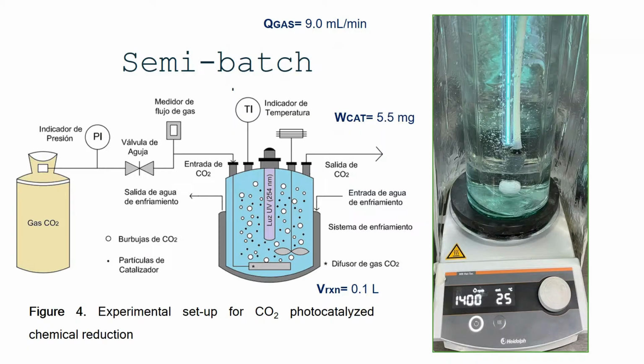There is the bubbling. If you try to do this reaction, the gas diffuser characteristic is essential because of the gas bubble size and also the gas flow. And one might think, one that is not an engineer, might think that if you input more gas, that's going to be better, but it's not because of the residence time. You need a low CO2 gas flow, so you can obtain a proper residence time so the CO2 can dissolve into the solution.